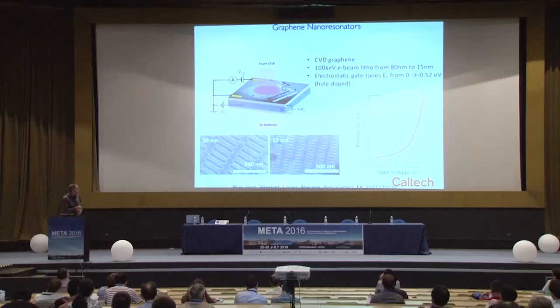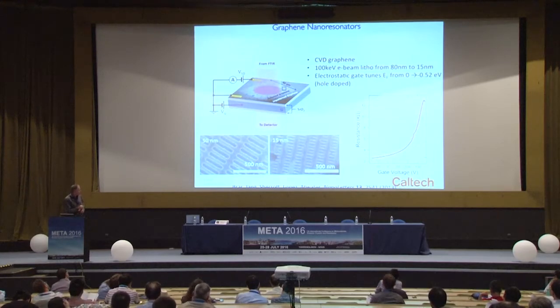So graphene is a very weak absorber, and we can see this in single pass transmission experiments. So in order to achieve higher absorption in graphene, we can produce resonant structures. And we can make resonant structures by patterning graphene into thin ribbon resonators, which when excited by a transverse polarized normally incident wave, we can excite the lowest order electric dipole mode. In this case, we have a graphene sheet patterned using subwavelength, few nanometer scale nanoresonators in a large area ensemble.